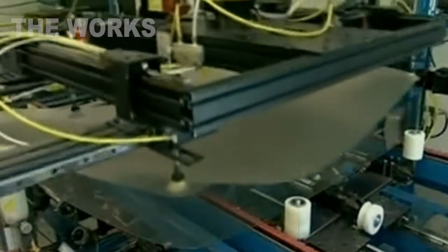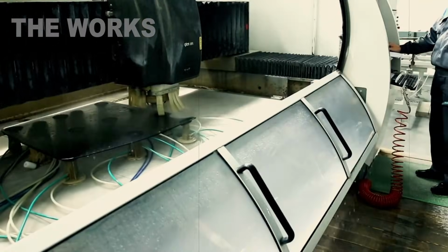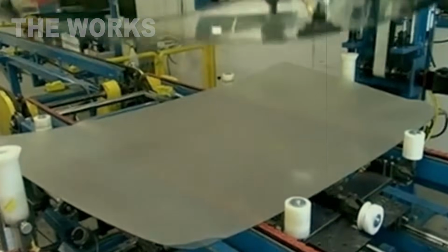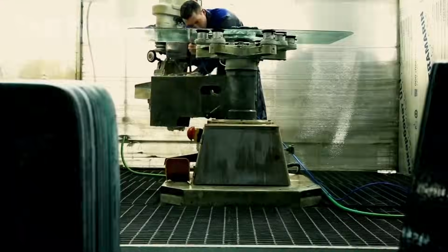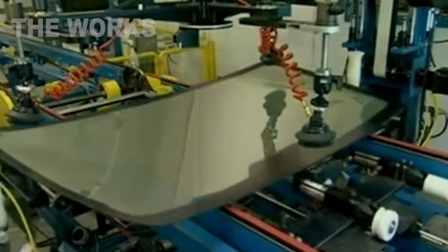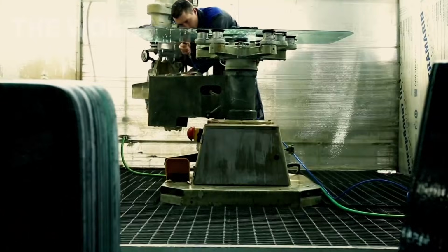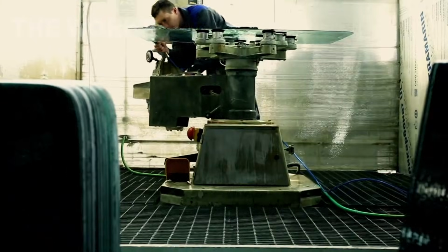After melting, the glass mass undergoes forming, which in modern production is most often done using the float process. Liquid glass flows out of the furnace and enters a bath of molten tin. Thanks to tin's high density, the glass mass spreads evenly across its surface. Under its own weight, the glass forms a perfectly flat and smooth surface. Gradually lowering the temperature, the glass hardens. By the time it exits the bath, it's ready for processing. The float method allows manufacturers to produce glass sheets with precise geometric parameters and high surface quality.